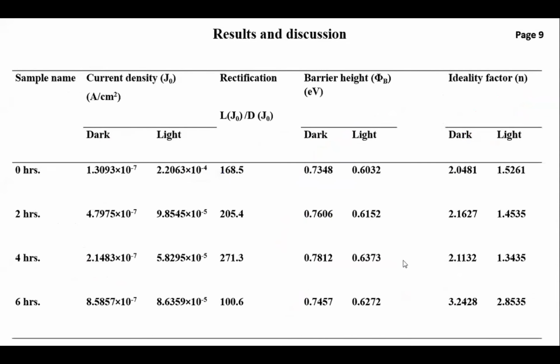For the first film, which is as deposited, there is a slight rectification of 168.5. After annealing, the film rectification value increased to 205.4. Then at 4 hours, it has a value of 271.3, which is the highest one. Thereafter, it starts to decrease to 100.6. And the barrier height under dark is 0.7348 and increases with increasing annealing period up to 0.7812. Thereafter, it decreased to 0.7457. After the films were exposed to light illumination, the barrier height decreased.